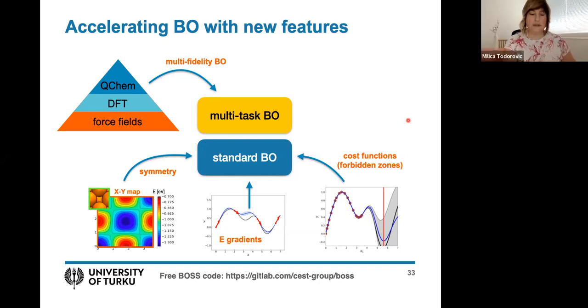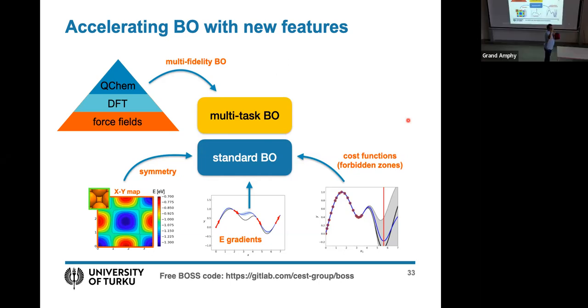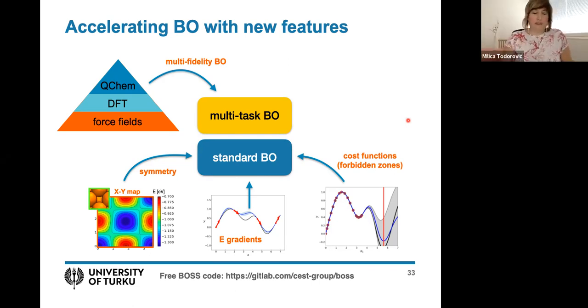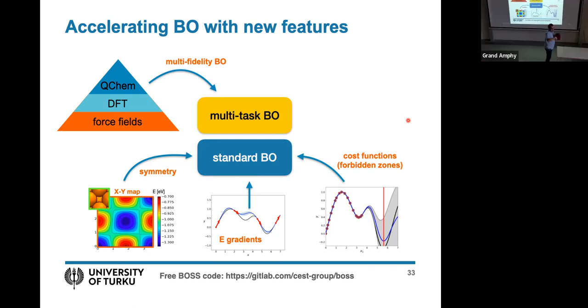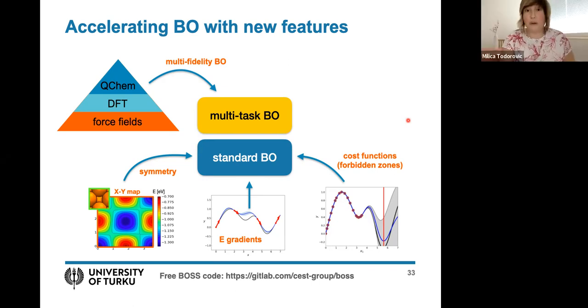Because, for example, we could imagine for your fullerene on anatase that you can make a small Monte Carlo simulation, explore, and then you relax it with DFT. You make a static DFT relaxation after. Yeah. So, very good question. We asked ourselves the same when we started this work.